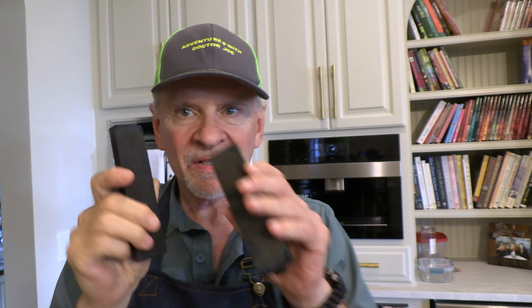So these jaws have now been refaced, skimmed on both sides, heated appropriately, oil quenched, and then we just washed them off in the parts washer. Now we're going to do some tempering. These are very hard now. They have a very hard surface, but it's probably a little bit brittle. So if we temper these, it'll reduce that hardness a little bit, but make these much more durable.